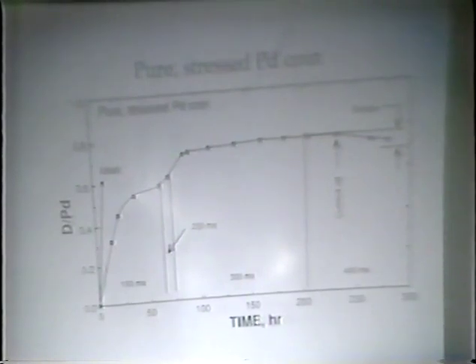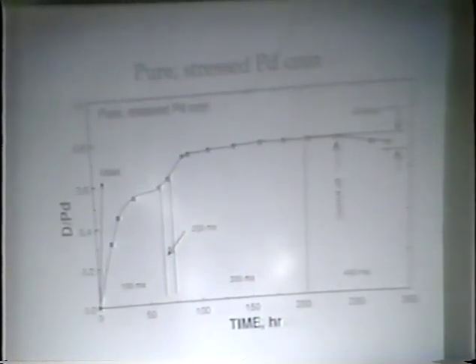But first, let's look at the behavior of palladium as you might get it off the shelf, pure on the surface, stressed because it was unannealed but rolled from this button. And this is a typical behavior that we experience, and many others have as well. You'll notice that the content of deuterium rose. It tended to level off. We changed the current. It went up again and then leveled off again.